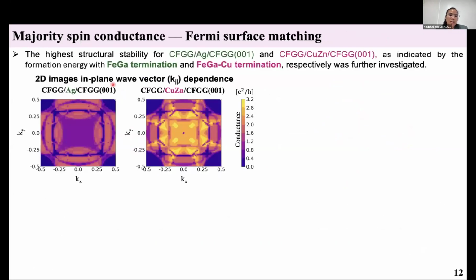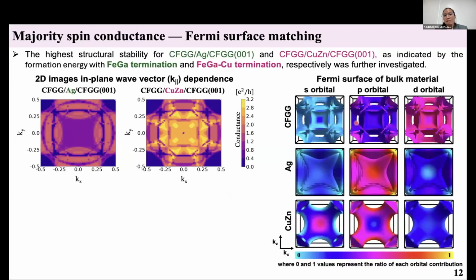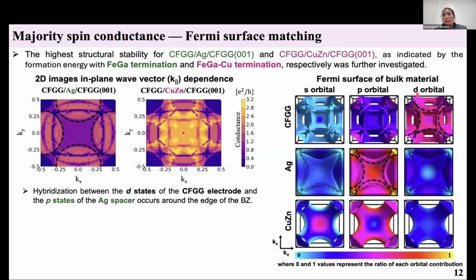So this is the 2D image of the in-plane wave vector k-parallel dependence in the Brillouin zone for the Ag spacer and copper zinc spacer. The yellow color represents the high conductance. For the copper zinc spacer, the highly conducting region spreads over almost the entire region. On the other hand, for the Ag spacer, the lower conducting region occurs around the edge of the Brillouin zone. Then to understand the orbital contribution, the Fermi surface of both materials was analyzed based on s, p and d orbitals as shown here. The conducting region for the Ag spacer is mainly due to the hybridization between d states of the CFGG electrode and p states of the Ag spacer around the edge of the Brillouin zone.